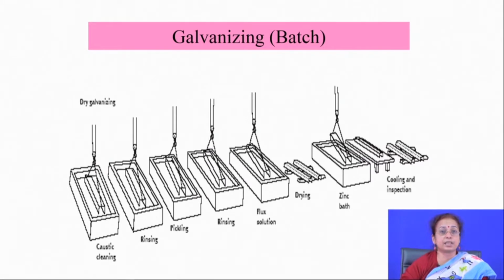Now, if you talk about hot dip galvanizing, as we mentioned in the other case, here also surface cleaning is a mandatory step which you should follow prior to hot dip galvanizing. You go for several steps of cleaning. When there are dirt particles or dust on the surface, you go for caustic cleaning and then rinsing, and if you have a lot of oxide layer on the surface, you should go for a pickling operation. In pickling you basically take 3 to 5% hydrochloric acid solution at a temperature of 35 to 40 degrees Celsius. You dip the component in the pickle reagent for 1 to 2 minutes maximum, then take it out and go for rinsing, and then your surface is cleaned.